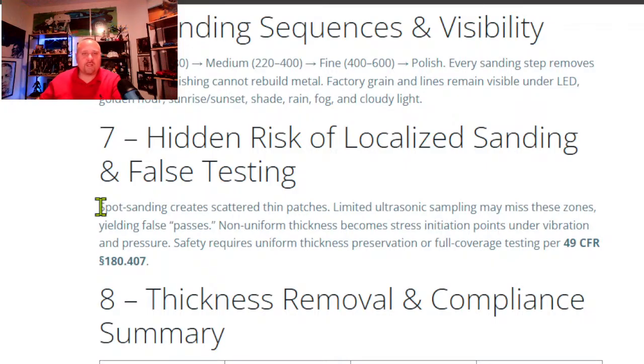When you see people sanding material, and it's not just tanks, but any material, if an area has more damage in one place, of course they're going to be more aggressive with sanding in that area because they're removing more material to smooth that surface out, and then that has to be feathered out. With that, you're going to have low spots all over the place. So this is where it comes into spot sanding, scattered thin patches.